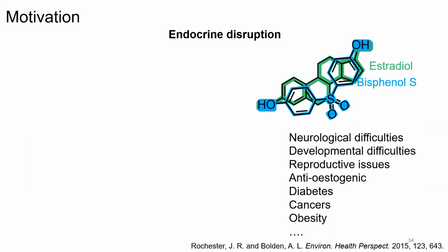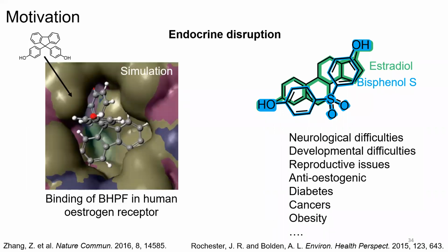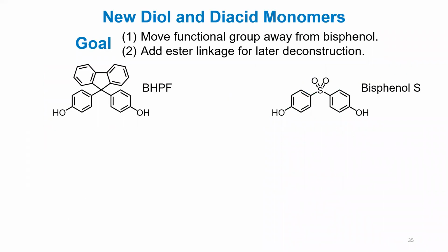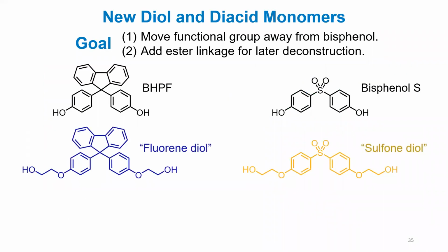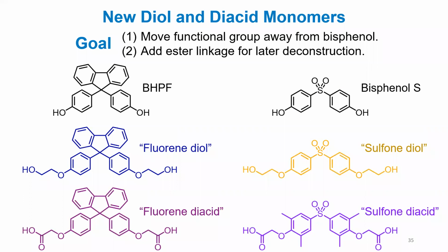And that's a problem. And some other literature is now showing that even the fluorene derivative can fit into the estrogen-like receptors, and that's a problem too. So we thought two things. One, these are really important functional groups to use, but can we do two things? One, let's try to extend the hydroxyl group away so it doesn't exactly overlap anymore with those two hydroxyl groups. And then two, let's make this biodegradable at the same time by using a step polymerization and then using hydrolysis. So not only should we make the diol version, but we should make the diacid version as